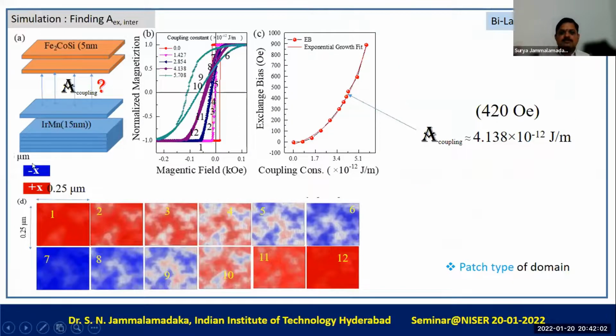So to understand more about the kind of coupling that exists between the antiferromagnetic iridium manganese and the ferromagnetic Fe2CoSi, we also have performed micromagnetic simulations using MuMax. What we could see is that we tried to vary the coupling strength between AFM and ferromagnetic layers, and at a different coupling strength, we tried to calculate the exchange bias values. As I mentioned, in our experiment, we could get the exchange bias value of 420 Oersteds.